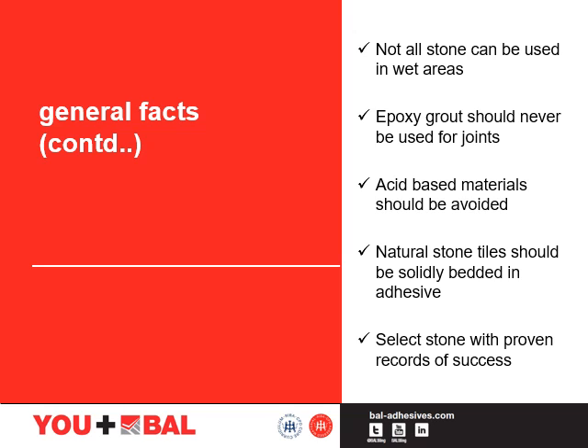Not all stone can be used in wet areas. Those susceptible to water uptake, staining and deformability should not be chosen. Epoxy grout should never be used for joint filling between units. Epoxy has very little flexibility and can cause excessive restraint when using natural stone. Acid-based materials should always be avoided — acetoxy curing silicones, for example — as acid-based compounds can attack natural stone surfaces and cause long-term damage. Natural tiles should always be solidly bedded in adhesives with no void beneath the tiles. Selecting stone that has a proven track record of success on floors and walls will help the success of the project.